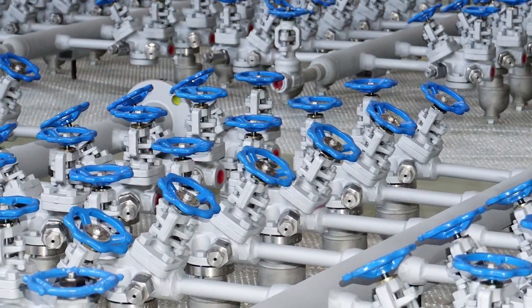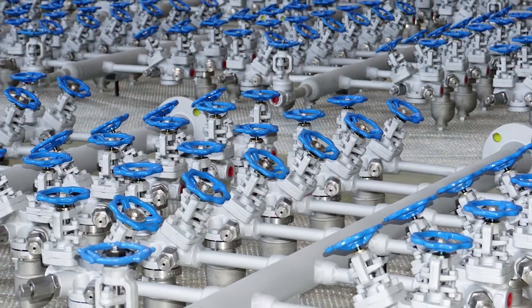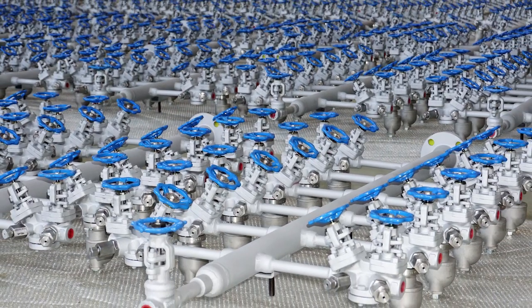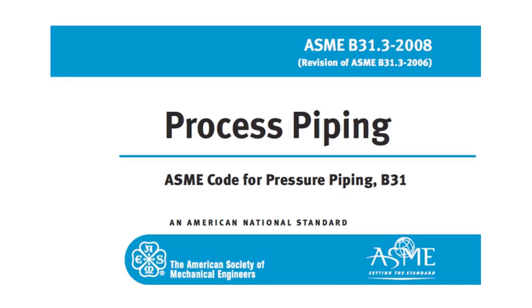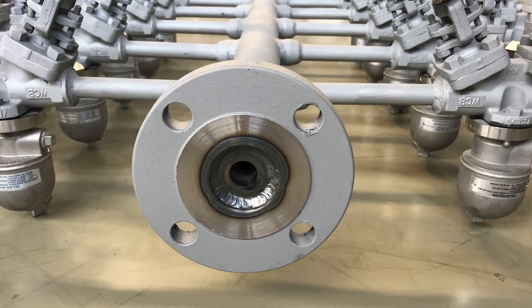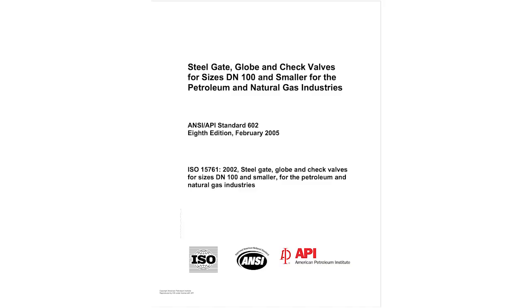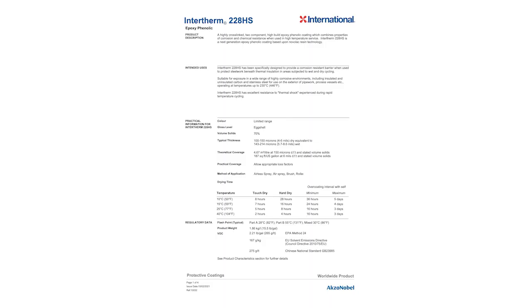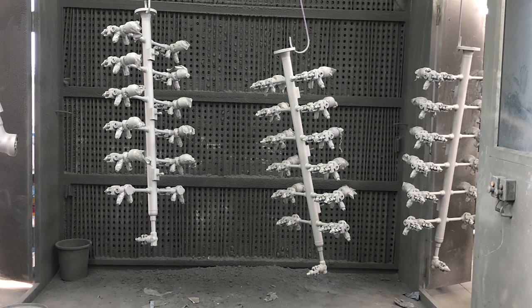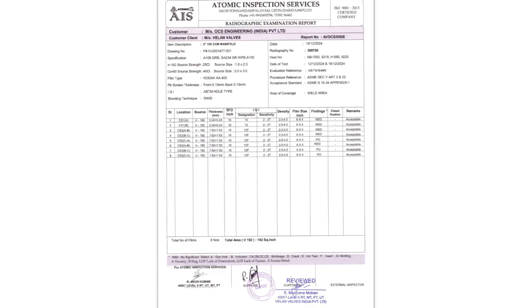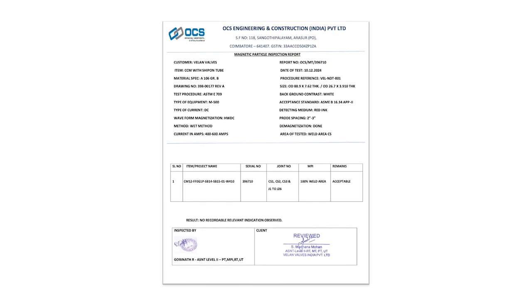To conclude, I would like you to remember a few things about Velan steam and condensate manifolds. Fully constructed in accordance with ASME B31.3. Internal siphon tube to eliminate water hammer and prevent freezing on all condensate manifolds. All valving is compliant with API 602 Class 800. Coated with Intertherm 228 epoxy phenolic coating. NDE 100% RT, PT, MPT.